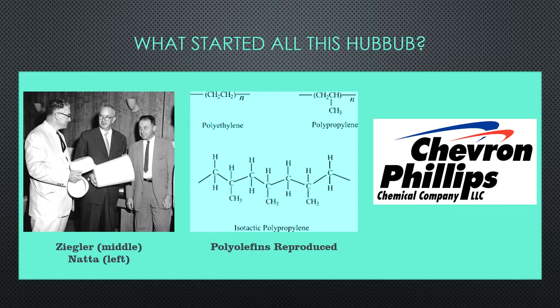This polymerization could now be done even at standard temperature and pressure. Before, polyolefin synthesis occurred at very high temperatures and pressures. Because of the low cost of titanium and the observation that titanium tetrachloride tripled the productivity of polymerization, titanium tetrachloride took off as a primary catalyst for the polymerization of ethylene. With the new titanium catalyst, polyethylene was successfully polymerized with high molecular weights.